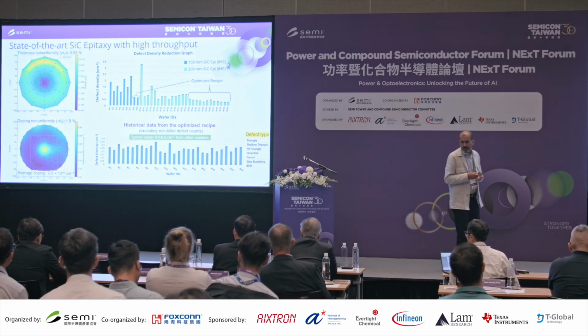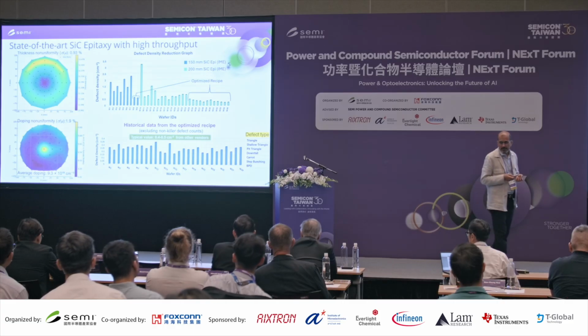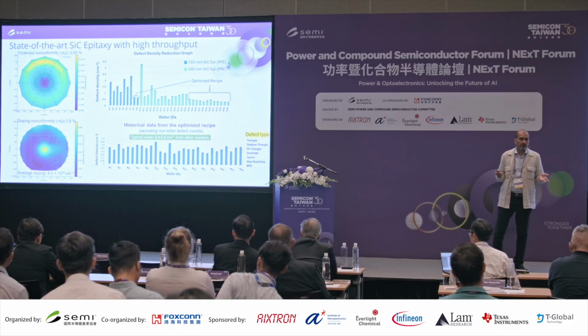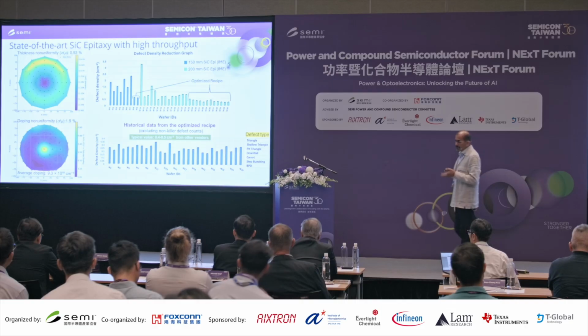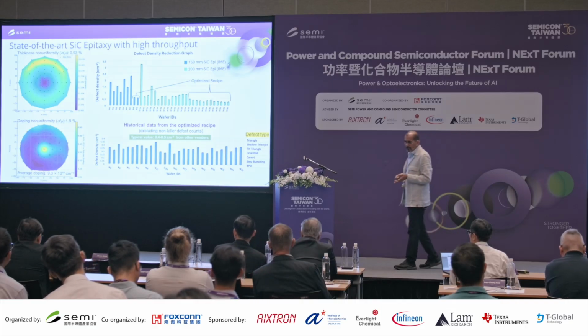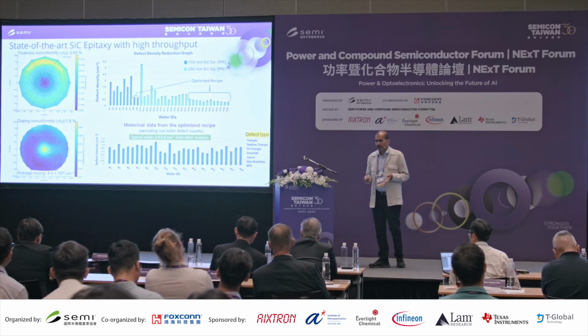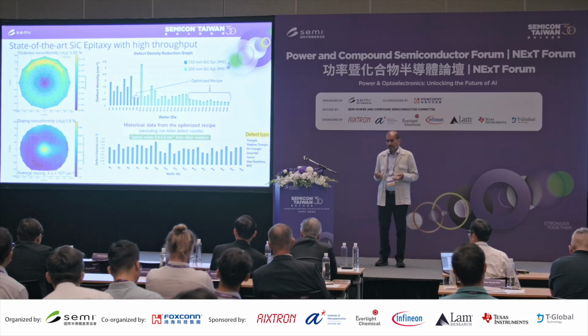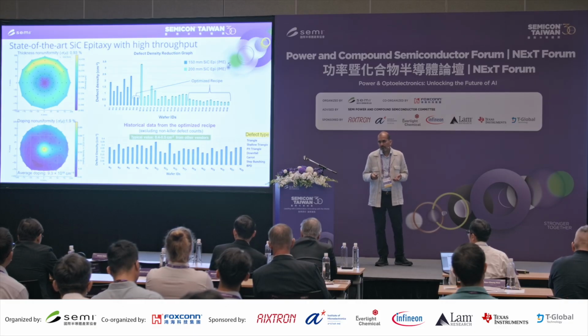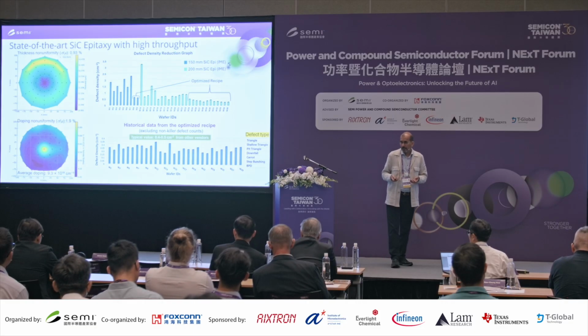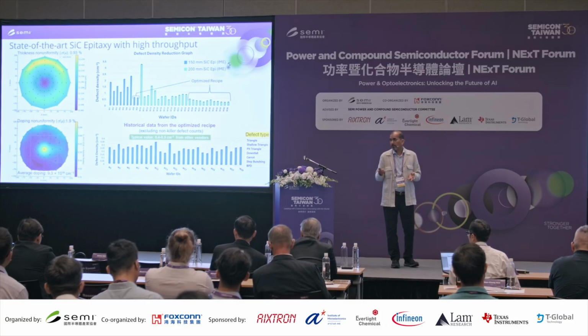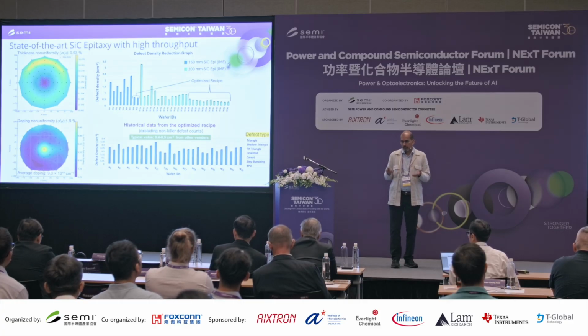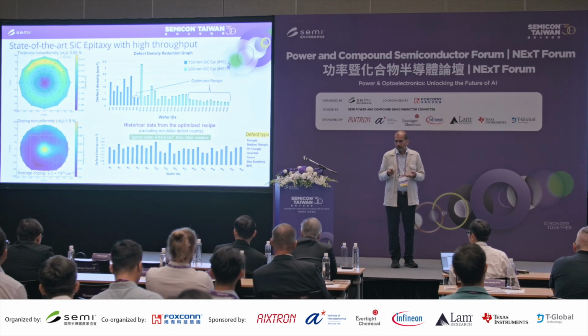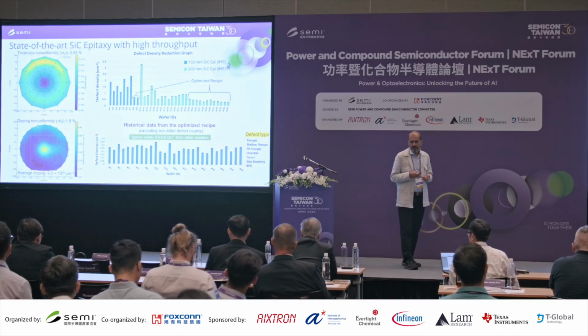What you can see here in the top bar graph, the blue is our qualification of the tool. From there, we started developing and improving our process, and you can see that we have finally developed a process with a defect count of better than 0.4 per square centimeter, including all the critical defects put together, which is one of the best-in-class epitaxy today for 150 as well as for 200 millimeter silicon carbide.